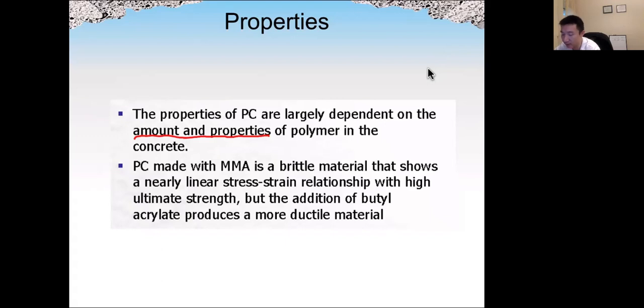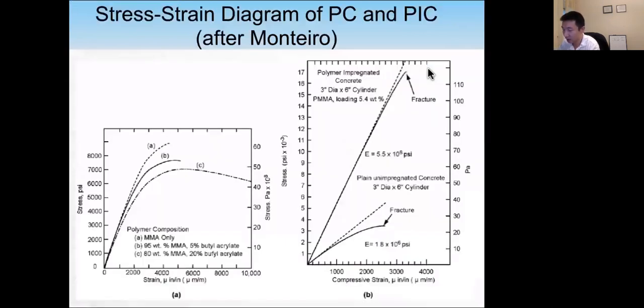For example, polymer concrete made with MMA is brittle, as you can see from the figures in these slides. Here are the stress and strain curves for polymer concrete: MMA only, or MMA with 5% butyl acrylate, or 20% butyl acrylate. As we can see, for these three types of polymer concrete A, B, and C, the final strengths and also the modulus of elasticity are very different, as well as the post-peak behavior.